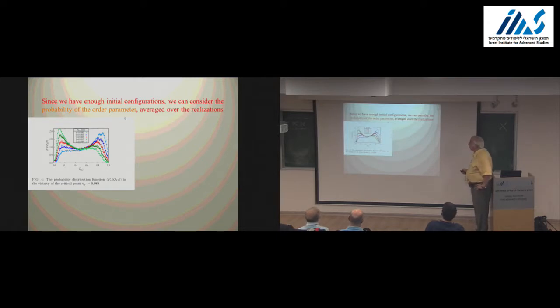You see, this is already near the transition. Far away, you have a peak around 1. Far away, you have a peak around 0. But here you have a very nice change where the probability to see the order parameter is at values close to 1 as long as you are not at the transition, and then close to 0 when you already passed the transition. But now look at this point. Look at this green line. There is an almost flat region. What is this flat region? In the theory of first order transitions, this is a spinodal point.